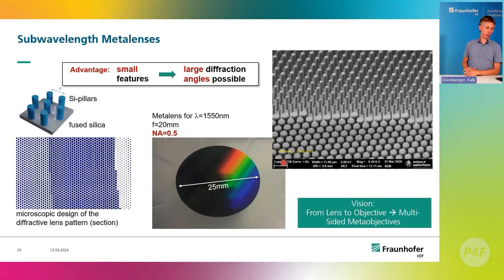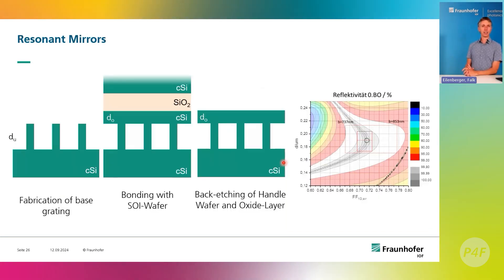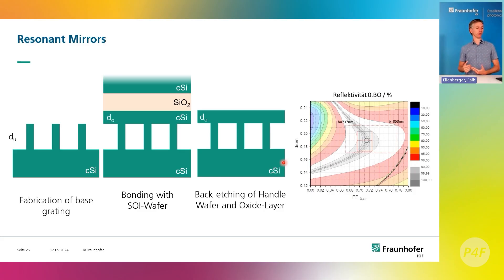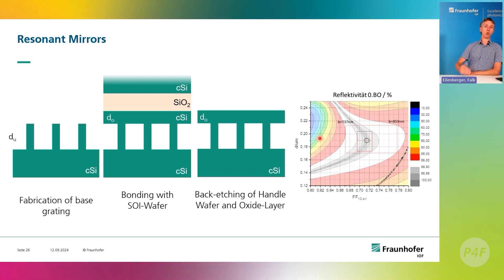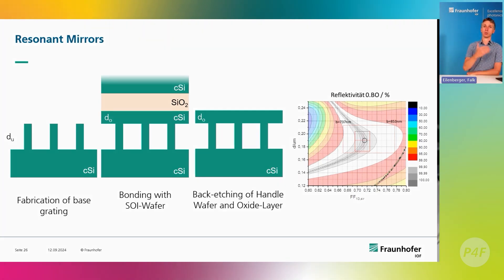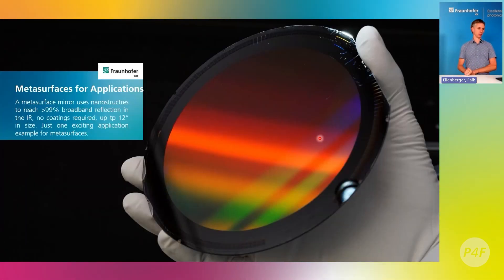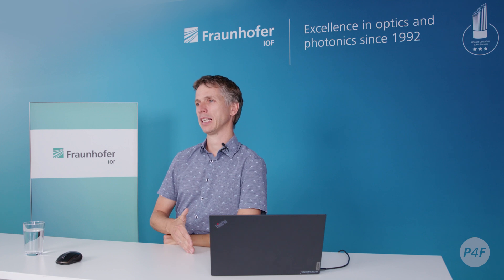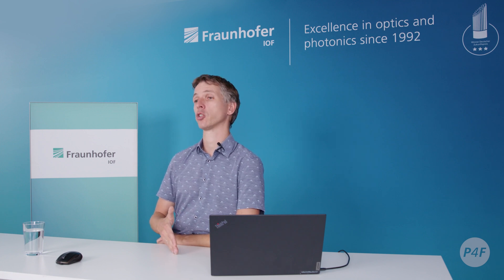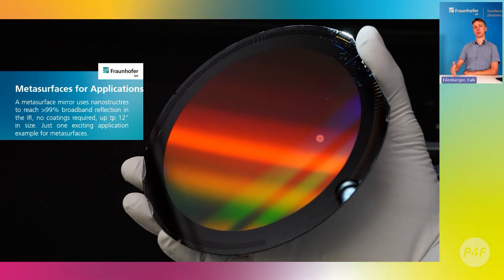We can also do meta lenses — discussed frequently — and more funky systems. We can create highly reflective metasurfaces where all propagating waves interfere destructively, so everything must be reflected. This is an example of a mirror made from pure silicon — silicon on air — with more than 99.5% reflectivity; the record is around 99.98%. This is an interesting new way to build mirrors from single materials that can operate in very harsh conditions where only very few materials survive.